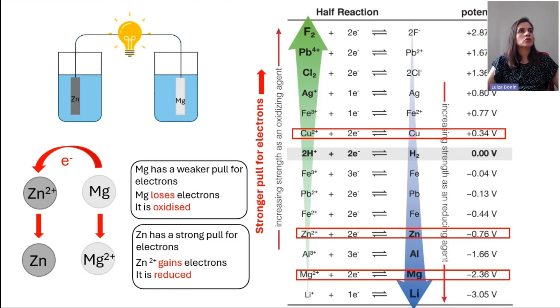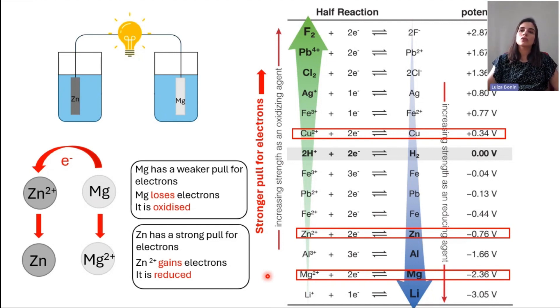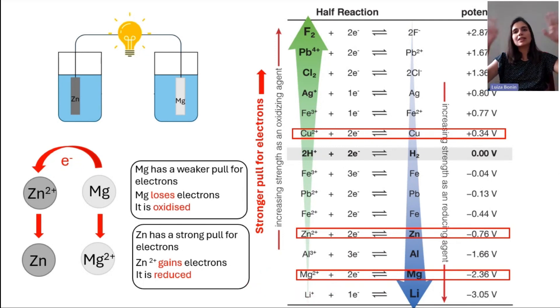This is interesting to know not just to create batteries, but also because we can use this to protect elements from corrosion. If we want to protect some zinc piece, we could connect a sacrificial piece of magnesium to it. And we know what will be corroding — oxidizing, losing electrons — is magnesium, and zinc will be protected. Also, if you look at the table, you see that lithium has a really special place — there is a good tendency to give electrons, and you probably understand this is why lithium is so good for batteries. It's not the idea today to talk about batteries, but I thought it was a good curiosity.